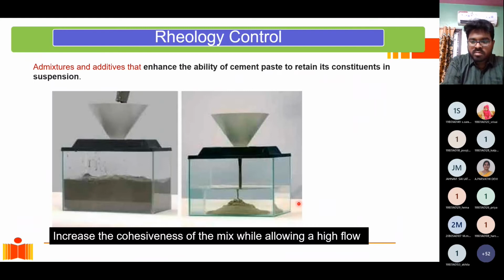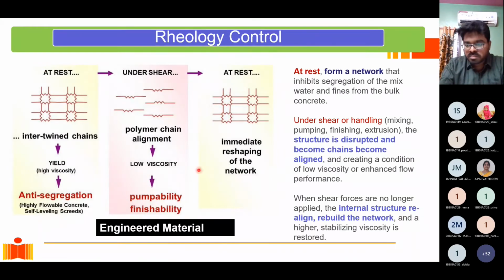Now, this is what we have to basically engineer. So if I take a normal concrete mixture and if I dump it into water, what will happen is that all the constituents will simply separate out. That's typically what will happen. Now, how do I keep the integrity of this material? I have to basically give it some cohesiveness that keeps these particles together. So I have to increase the cohesiveness of the mix while allowing high flow, what you see here. So it is flowing very easily, but even after going into the water, it is still cohesive. It's not getting disrupted. It is keeping all its particles in suspension. And that is basically this whole thing of rheology control.